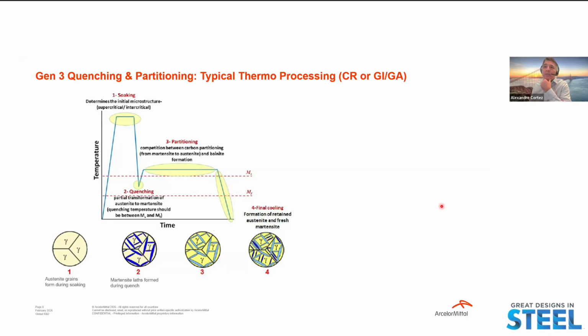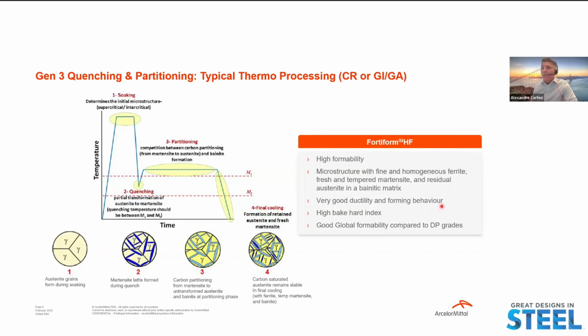And then we increase the temperature a little bit for the third phase, partitioning. This is a competition between carbon partitioning from martensite to austenite. In this phase, carbon partitions from martensite to untransformed austenite and bainite. And then finally, in the fourth phase, we have the final cooling. This is where formation of retained austenite and fresh martensite happens. And we have basically carbon-saturated austenite that remains stable in the final cooling, with a high temper martensite and bainite. This brings the steel high formability, very good ductility and forming behavior, high bake hardening index, and a good global formability compared with the first generation of DP grades.